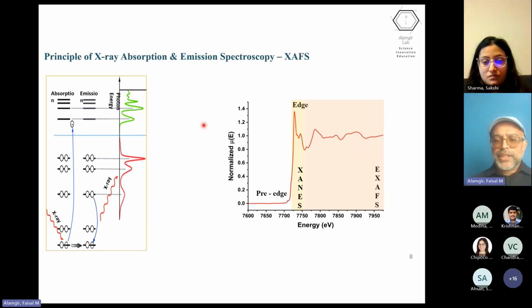Looking at X-ray absorption in a bit more detail, here's what it looks like. The X-ray absorption spectrum will essentially be measuring how the X-rays are absorbed by your material. And so if you plot that on a normalized scale, what you'd expect to see is that not much is happening until you reach that threshold energy where the core electron is released, and then you have all this information that is above the so-called edge. And so the edge is basically the energy required to reach the Fermi level for a core electron. And then the near edge region is basically giving you the details of the unoccupied densities of states.